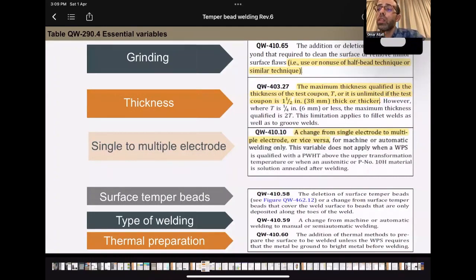Another essential variable is grinding. What they mean here by grinding is not that sometimes you apply the first bead and need to do grinding or remove some surface flaws or minor flaws. That doesn't mean it's not allowed. But grinding means the use or non-use of the half bead technique. So if the test coupon was qualified using grinding or the half bead technique, you cannot use the same WPS for the full bead technique.